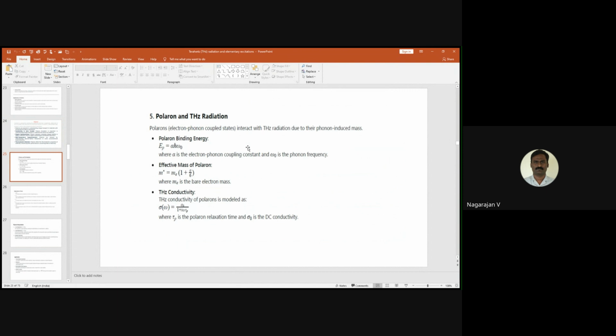in unconventional superconductivity. Okay, so polarons and terahertz radiation. Electron-phonon coupled states interact with terahertz radiation due to their phonon-induced mass. This is the polaron binding energy, alpha h omega naught, where alpha is the electron-phonon coupling constant and omega naught is the phonon frequency. Here m star is the effective mass of the polaron, m star equals m e times 1 plus alpha over 6, where m e is the bare electron mass.